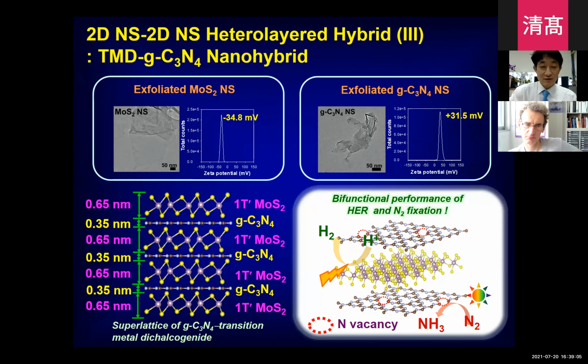We synthesize a lot of heterostructures, but as I told you in the introduction section, LDH is the only cationic, positively charged inorganic nanosheet. So normally we adopt LDH nanosheet as a cationic component, but recently we found that carbon nitride is a very interesting and valuable building block, because we can tune its surface charge by tuning the pH of the suspension. By lowering the pH, we can get the cationic carbon nitride nanosheet. So by using that, we synthesize a hetero-layered structure by reassembling with the anionic MoS2 nanosheet.